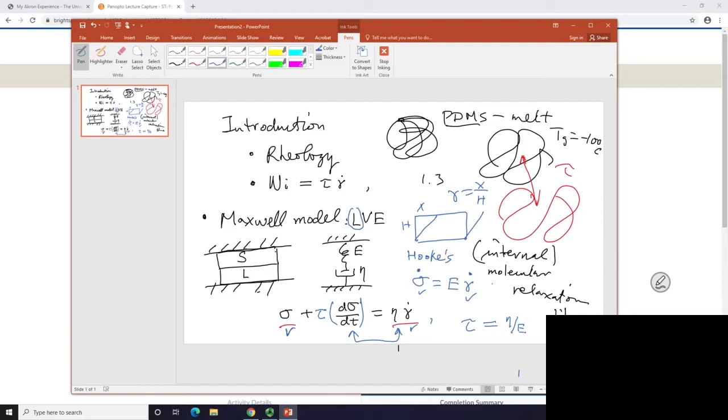So magically, this master, Maxwell, played a piece of magic by considering two elements, solid and liquid. He came up with this treatment where a time scale arises naturally. It is related to the viscosity of your material and the modulus, which is a sense of stiffness, a solid state property of it.